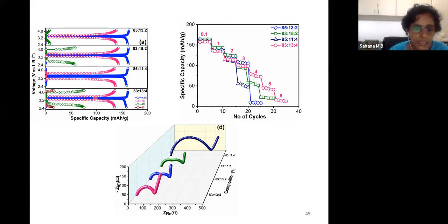Now that is minimum in case of 83-13-4, whereas when you increase the active material to 85 and reduce the carbon content to 11%, then you can see that now here in the second graph where the laser pointer is, charging happens at still higher voltage, discharging happens at still lower voltage. So the loss in energy is more in this case.